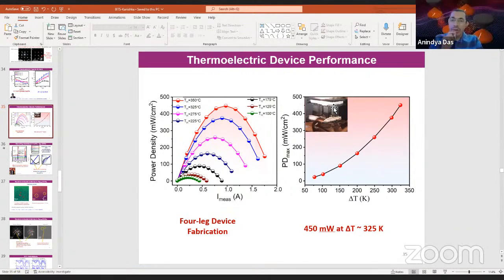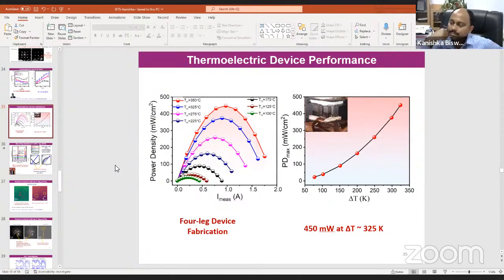Okay, I have one basic fundamental question. Sure. You said that there are small ordered structures in a sort of disordered environment. Of course, they are small ordered structures, but they are not aligned. Right. But if I think of something like a Moire superlattice, for example, will that not also play a similar role? Because if I have a Moire superlattice, my Brillouin zone becomes smaller, because I have an ordered structure at a different size, much bigger than the lattice constant. Once the Brillouin zone is squeezed, my phonons will be hybridized, so I have more phonon scattering, three-phonon processes and all. Does it also help to reduce the thermal conductivity?